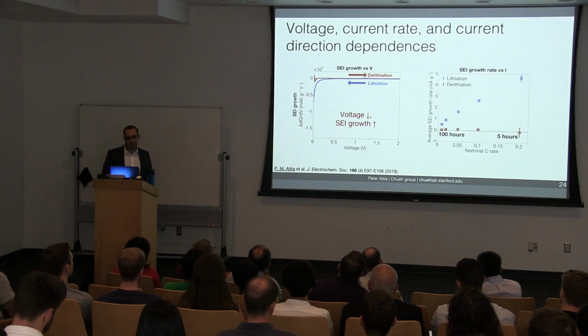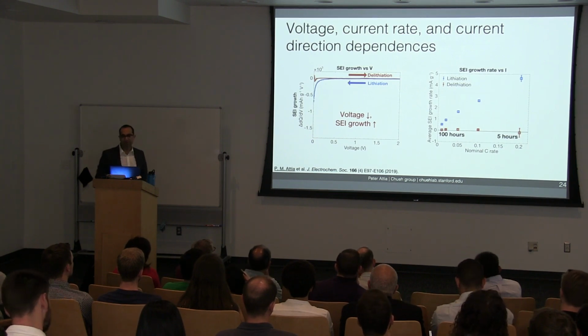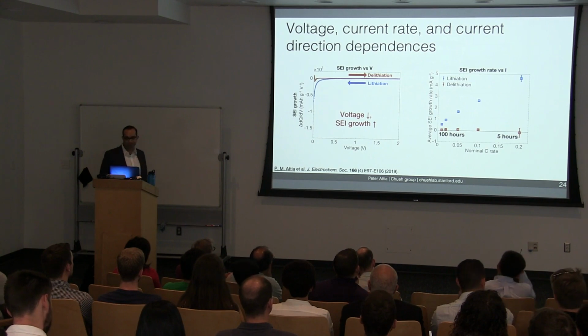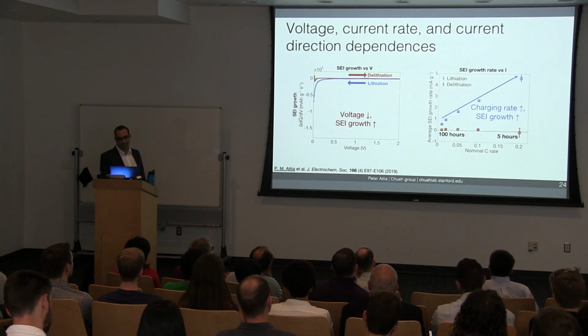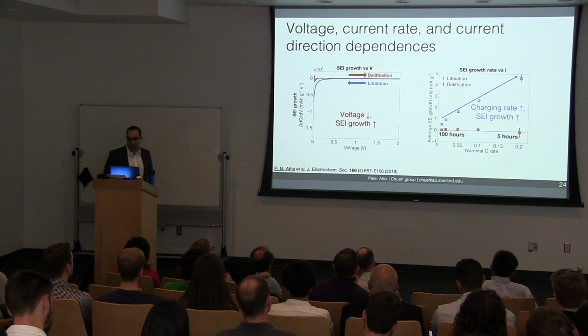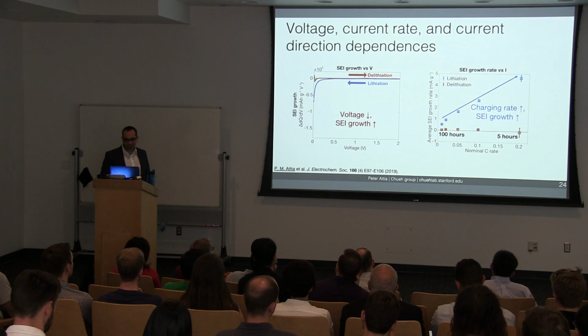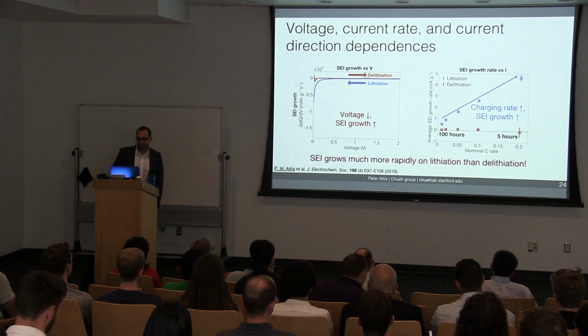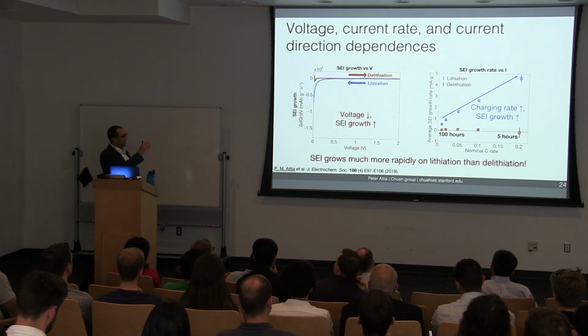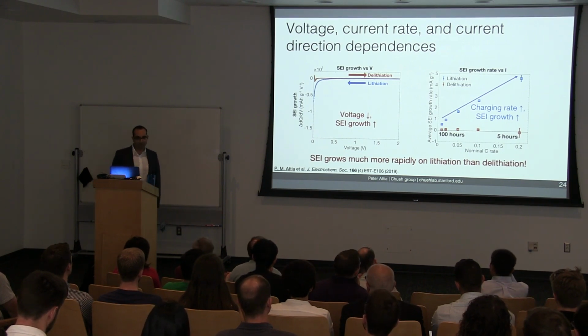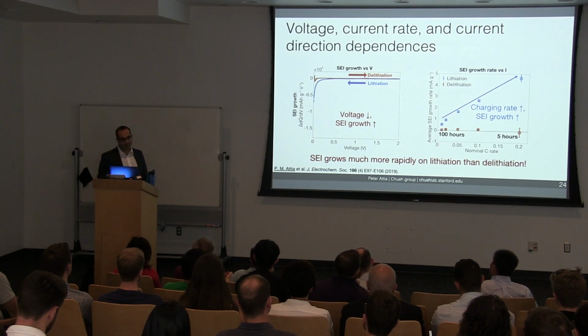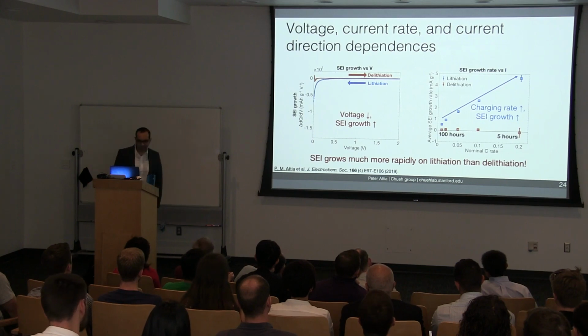I then measure the SEI growth rate as a function of the applied cell current. The left is slow cycling, 100 hours per cycle, and the right is relatively fast cycling, 5 hours per cycle. We see that SEI growth rates during lithiation increase with faster cycling. As an aside, this might be important for SEI growth during fast charging, so keep that in mind. However, the most striking part of this result is that SEI grows much faster during lithiation than during delithiation. This is quite surprising because the driving force for SEI growth is similar in both directions. So we'd expect similar SEI growth rates in both directions as well.